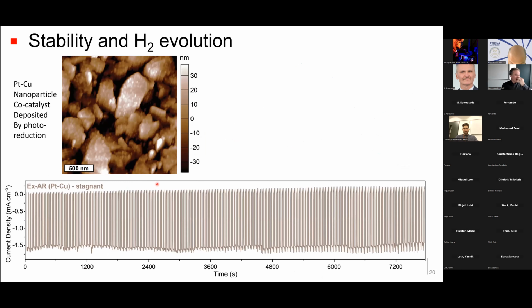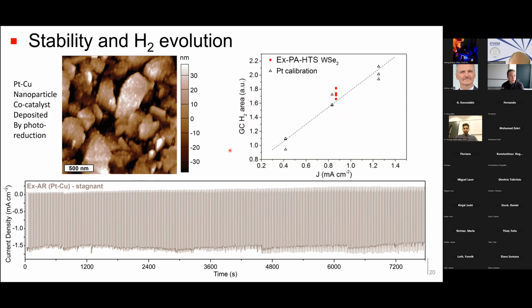I should note that to achieve the hydrogen evolution, we put a platinum copper-based co-catalyst on the surface, and we can measure very stable performance. We can use a gas chromatograph to measure the hydrogen coming off to show that it's 100% Faradaic efficiency.